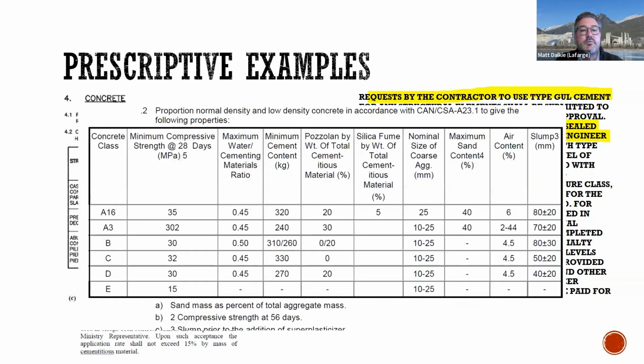Here's another example, which is a very restrictive and prescriptive specification. Again, you've got the compressive strength and the maximum water to cementitious materials ratio, but they also provide a minimum cement content and maximum pozzolanic material content. That would be your fly ash and slag. They give the nominal coarse aggregate size, but they even go down and say how much sand needs to be in a particular mix as well. So these are very prescriptive. That's an example of a very prescriptive specification.